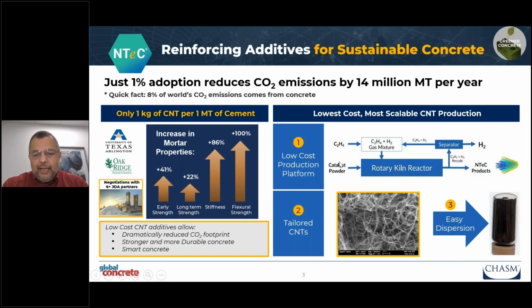Our CTO has certain proprietary mixes on the catalyst powder, which makes it possible to use a rotary kiln to make nanotubes. And then the next challenge, of course, when you make it at large scale, we put ourselves a target. Cement today is at a marginal cost of $50 a ton as made by the cement manufacturer and sold in the market at $100 to $150 a ton.